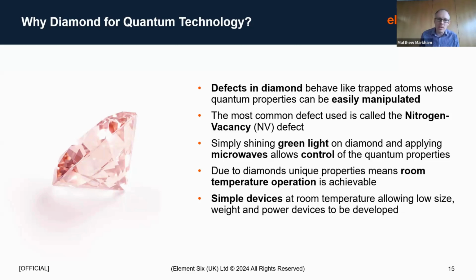The second important point about defects in diamond for quantum applications is they're very easy to manipulate. With the nitrogen vacancy defect, you can control the spin simply by shining green light onto it and microwaves, and that allows you to put it into states called superposition, or create entangled states between multiple defects. That's very simple control, and as I mentioned, you can do this at room temperature. The control mechanisms, the light and the microwaves, are all very simple things to apply, which means you can create a very simple device that operates at room temperature, allowing for low size, weight and power devices to be developed.